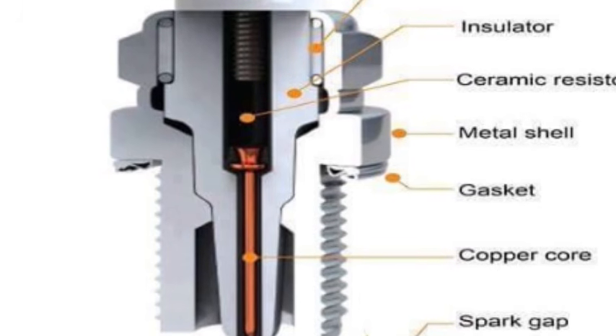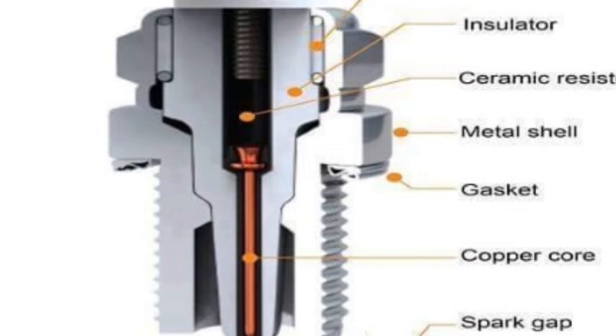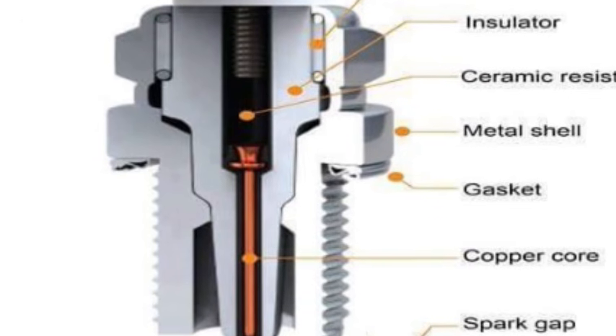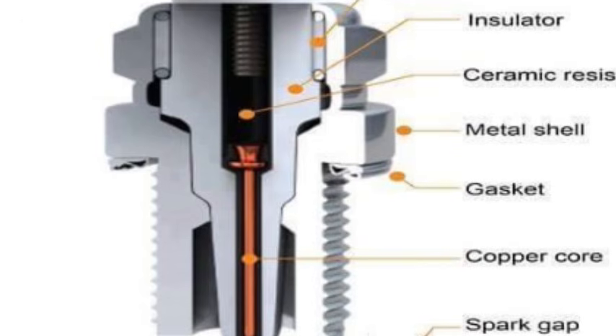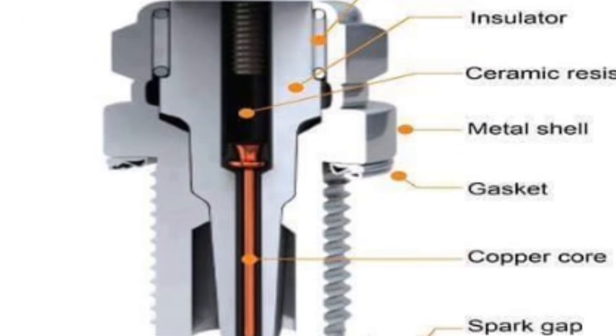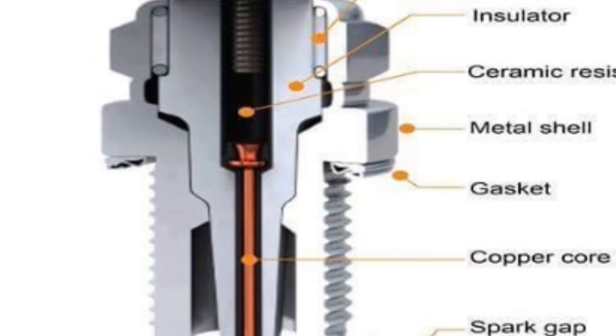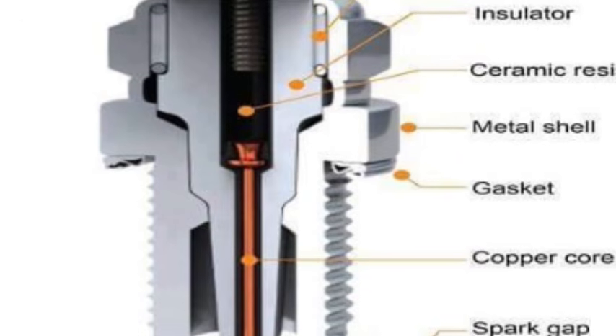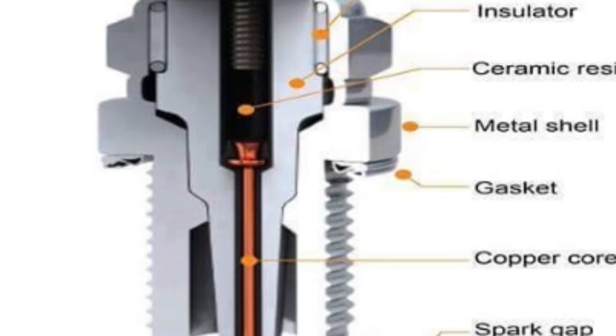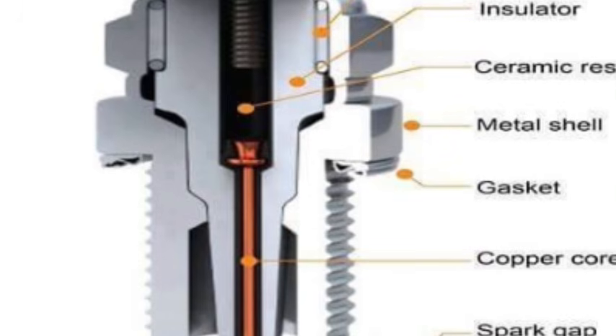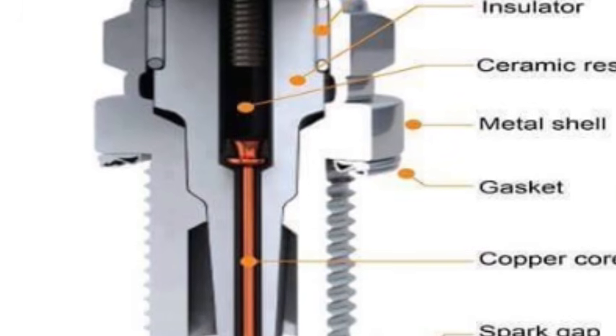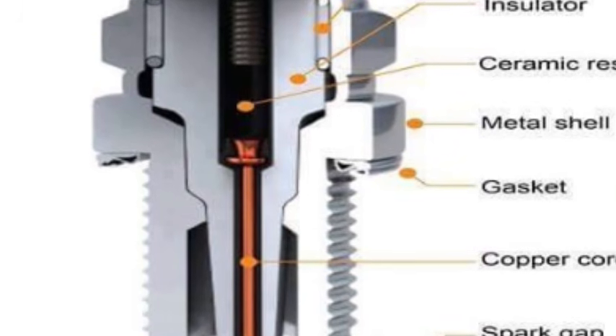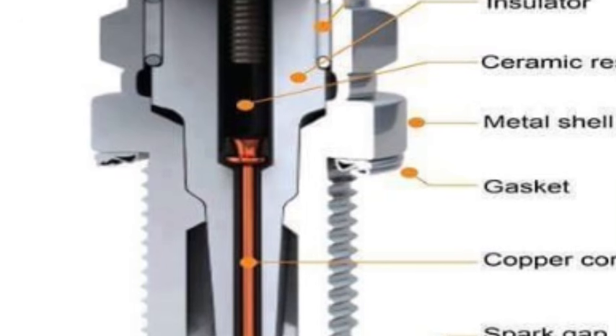If the firing end runs too cold, fuel and lead deposits build up and foul it, shorting out the spark. If it runs too hot, it causes preignition, which can destroy the engine. The spark plug must thread this needle, staying hot enough to burn off deposits but cool enough to avoid preignition inside a combustion chamber that is trying to cook it 50 times a second for hundreds of hours.